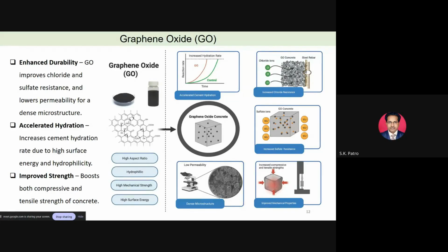And similarly, it helps accelerate the hydration process, like your nanosilica, which also increases cement hydration rate due to high surface energy and hydrophilicity. Because of hydrophilicity, it quickly attracts the water to it. Prior to other ingredients attracting the water, in that process it accelerates the hydration process. If you look at the plot here, time versus reaction rate, the graphene oxide takes less time for more reaction. In the control, it takes more time to get a similar level of reaction rate. So that benefit we are gaining from graphene oxide.